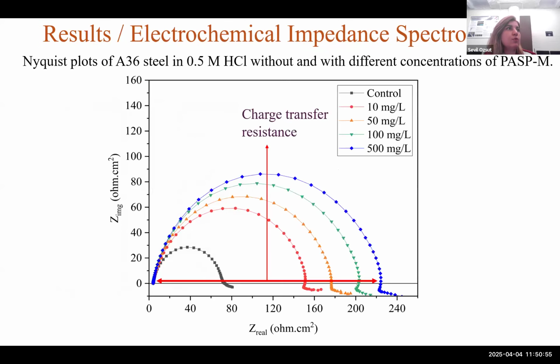For this reason, we did the electrochemical impedance spectroscopy test. This is the Nyquist plot of the steel specimen in hydrochloric acid again, but with different concentrations of the inhibitors. The radius of the Nyquist plot shows the charge transfer resistance, and a higher charge transfer resistance indicates less electron exchange. I mean, there's more resistance to the electron transfer.